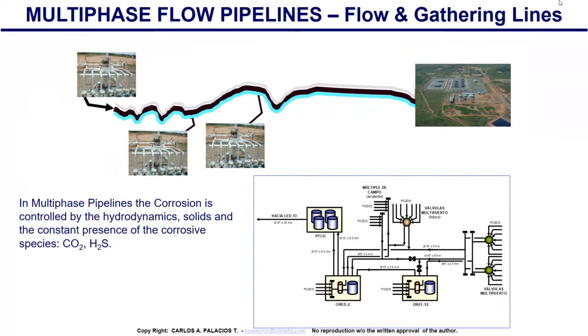We have a multi-port valve here collecting fluid from different wells from this area, and then from this area, and then from this area. 16-inch pipeline. The flow here was stratified flow, barely moving. Here, because it's an incline, stratified slope and slope, very high corrosion rates. And as I go, the more fluid goes into the line, and in this area the pipeline was almost full. No corrosion. From here, terrible, here, terrible. Go back to the same.